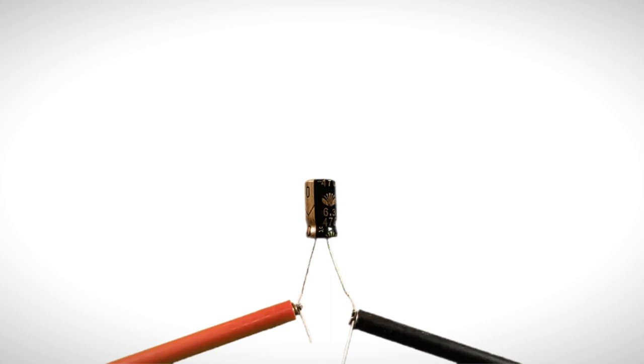If the voltage to a capacitor is applied the wrong way, the effect of anodic oxidation will reverse. This means the capacitor starts to degrade the oxide layer on the anode and to build up a layer on the cathode, which means a relatively high current will flow. This leads to heat, which vaporizes the electrolyte between the two plates. And as we know from physics, vapor needs a lot of space, which leads to an explosive end.